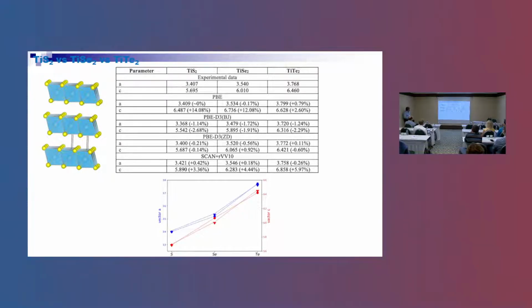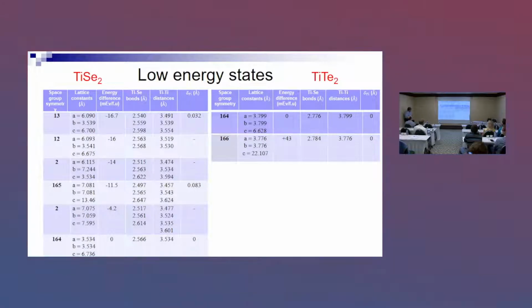There are some technical issues with all the dichalcogenides and basically all van der Waals materials, because of the large distance and because of the van der Waals forces, you need some correction for these van der Waals forces in the calculation we use. And basically this is the result for titanium diselenide and titanium ditelluride.